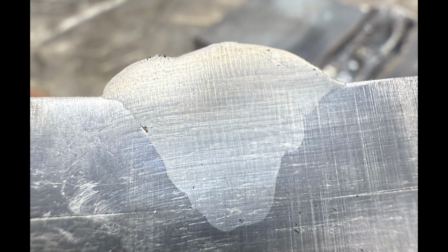Now, all of these passes, I did a drag angle and kept the gun parallel with the joint. I wasn't focusing the wire on the sidewall at all. Had I changed the technique slightly, this might not have happened. But again, it goes back to what I said earlier, that the short circuit MIG process is just unreliable at achieving sidewall fusion. And who knows, I didn't cut this plate in more places than what you see here, but it's entirely possible an inch from this point looks completely different.